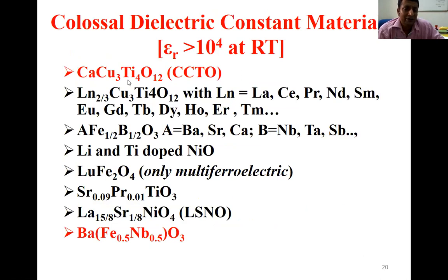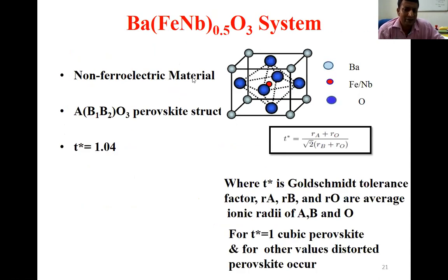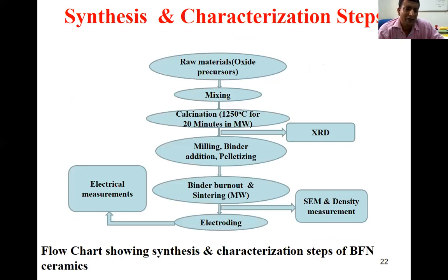These are two known non-ferroelectric materials, CCTO and the BFN. They have very high dielectric constant at room temperature, more than 10,000 at 1 kilohertz frequency, and of course their loss is high. But that is what we want if we want to process these materials. This is just the basics about the BFN system. It has a perovskite phase, and initially there was some controversy about whether it is a ferroelectric, but it is established that this is a non-ferroelectric system, because the earlier understanding was that only ferroelectric materials can have the high dielectric constant.